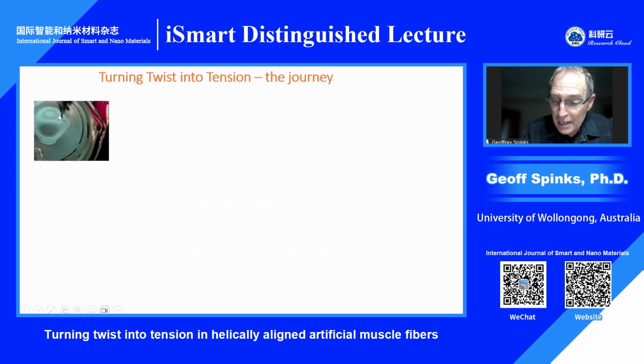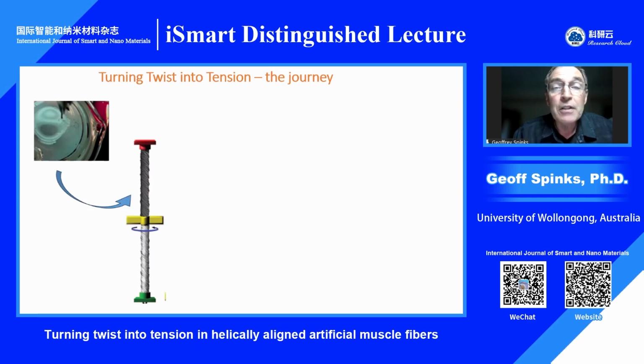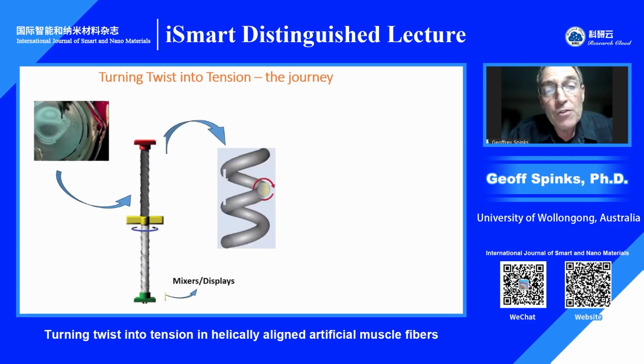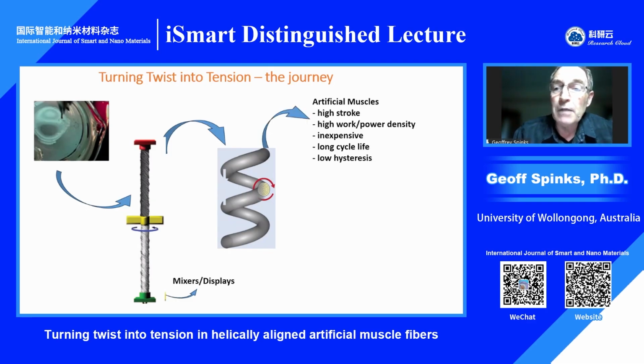So the journey so far has been very interesting over the last 10 or 15 years, really, since our first observation of rotating carbon nanotube yarn fibers in a beaker, which led to the development of high stroke torsional artificial muscles for the first time, and then some applications for those materials. But largely the most important application is the driving force in these twisted and coiled tensile artificial muscles, which make really great artificial muscles with really good performance, made from cheap and readily available materials, and many other positive attributes.